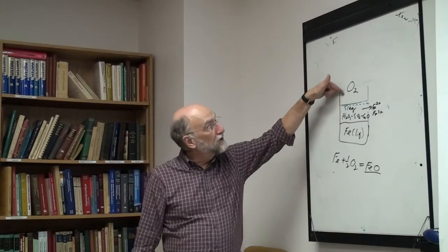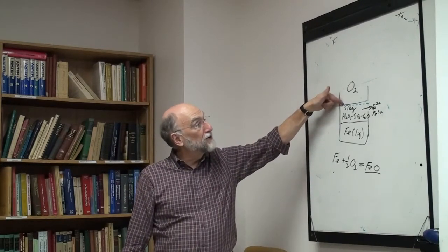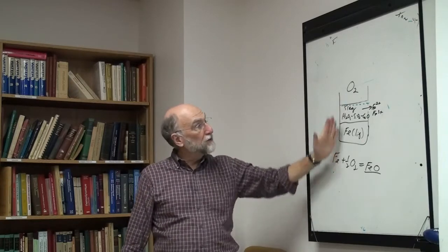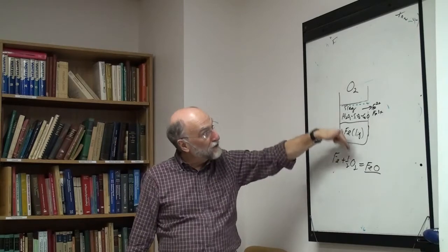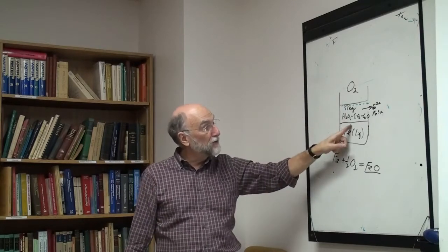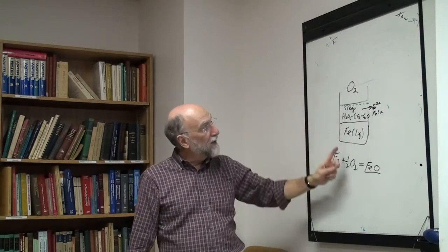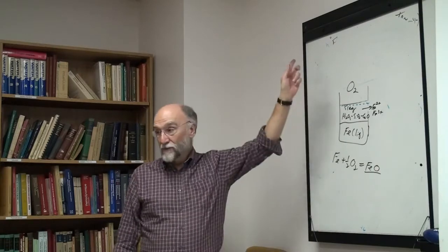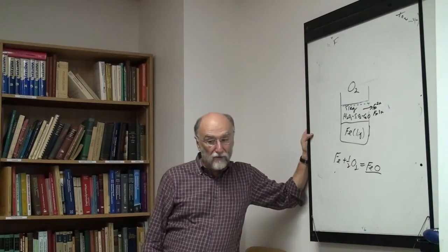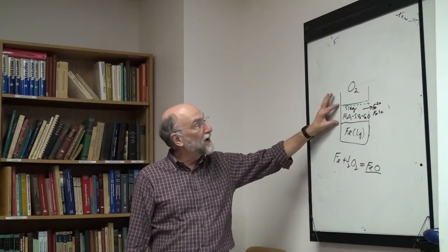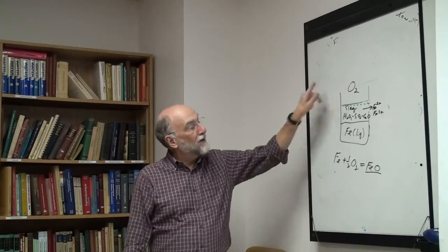Okay, so the oxygen atoms land on the surface, pick up 2 electrons, which move through the slag, and now they become oxygen ions, which can diffuse down. Same thing with the iron. It loses 2 electrons into the slag, and it loses an iron ion up through the slag. So if you take your slag with no reducible species, no species that have 2 oxidation states in the slag, your reaction will be very slow unless you have an external circuit.